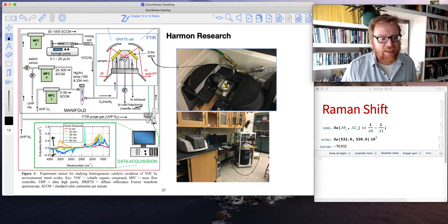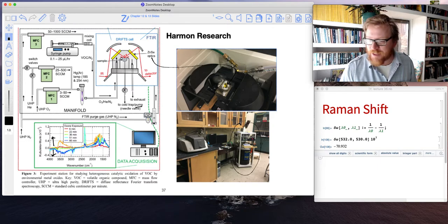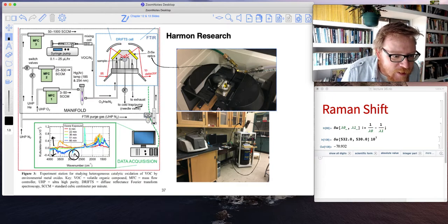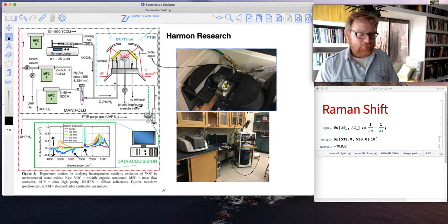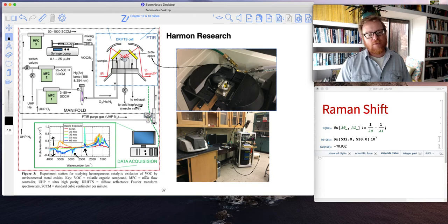You can see at 6 minutes of ozone exposure to some solid interface, some hydroxide stretches grew in. At 22 minutes, hydroxide stretches grew in even more. But then interestingly, at 36 minutes, they all went away, and at 51 and 66 minutes, we lost all of those hydroxide stretches. You can see we also lost some carbon-hydrogen stretches as well. You can see here, that's the gain of CO2. So we can study lots of complicated chemistry in real time using this technique.